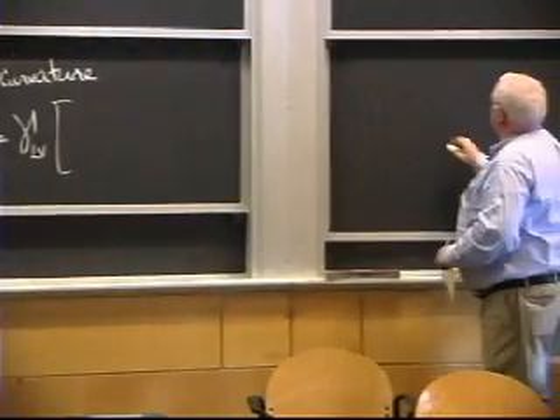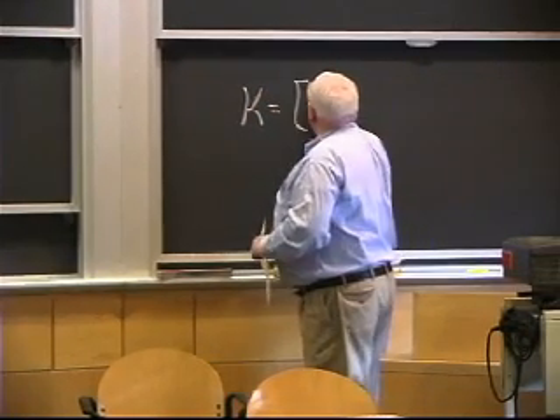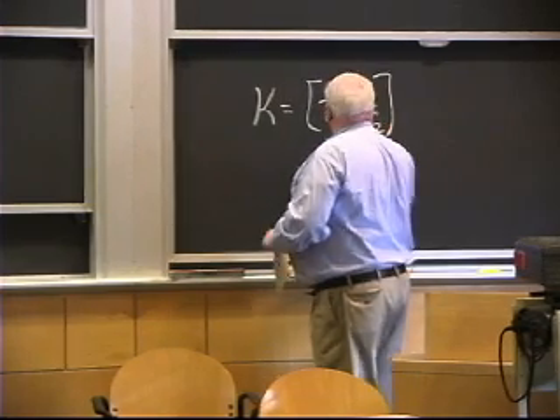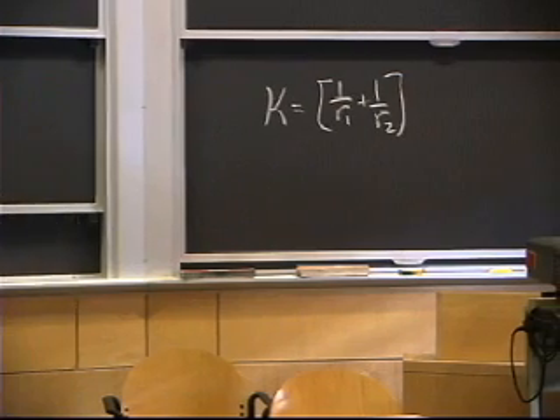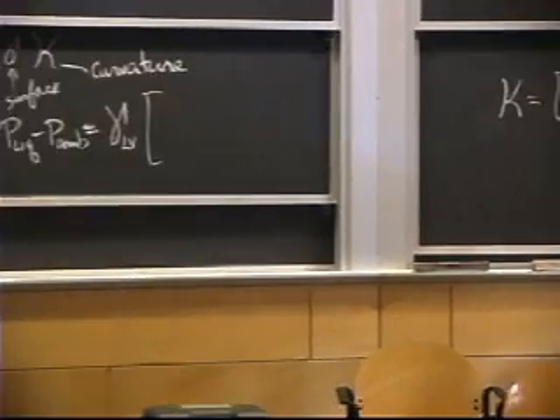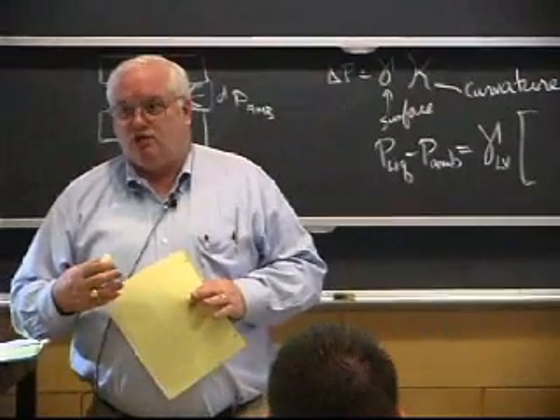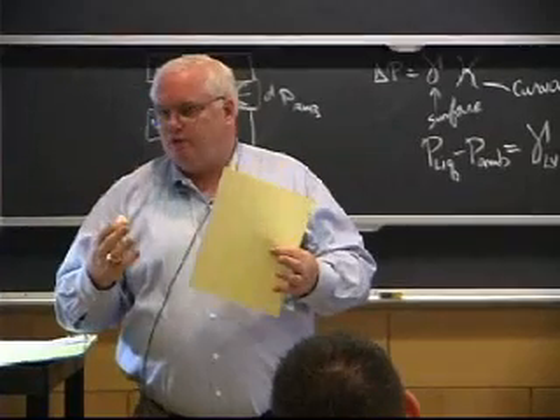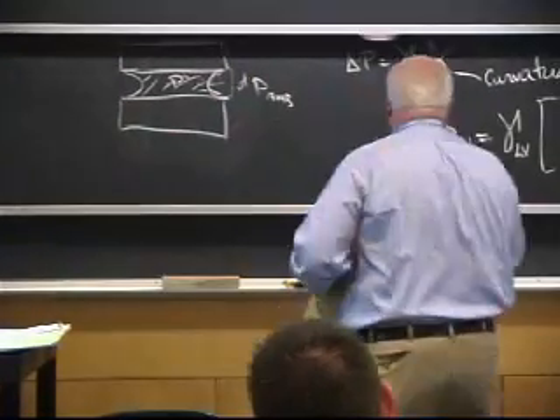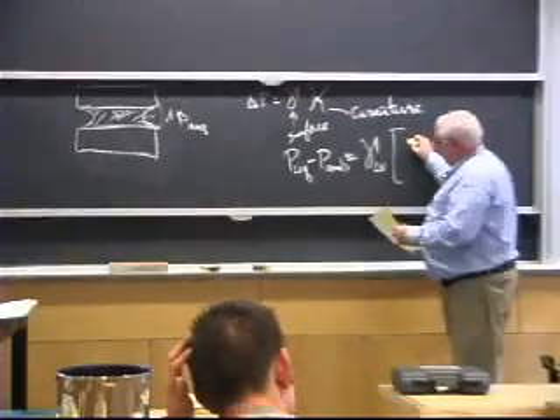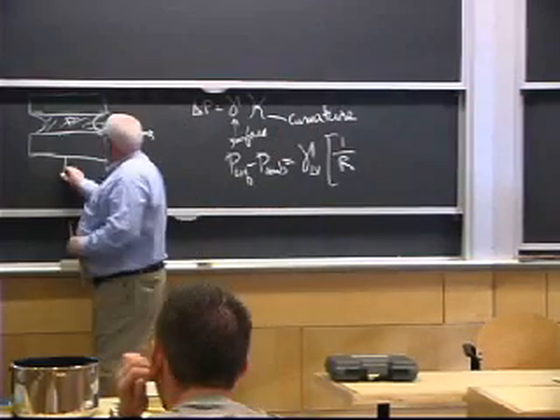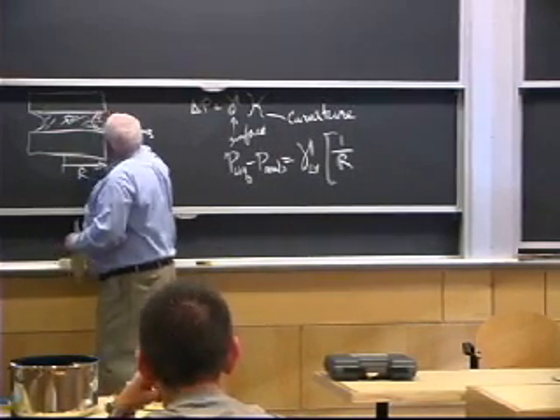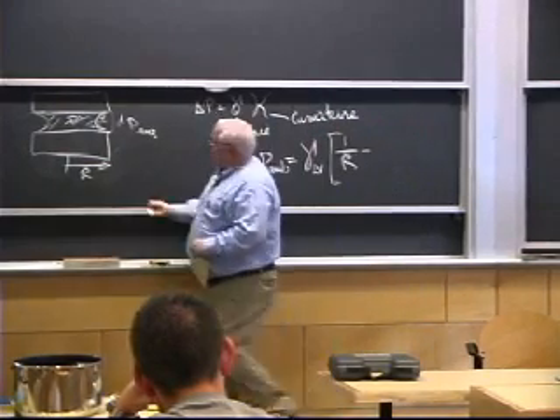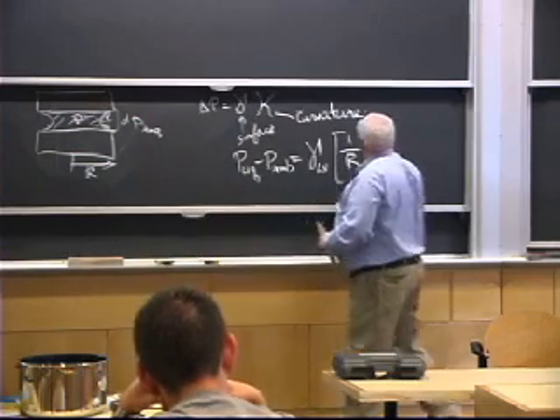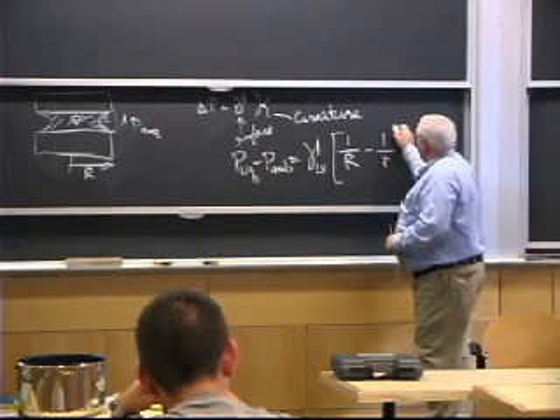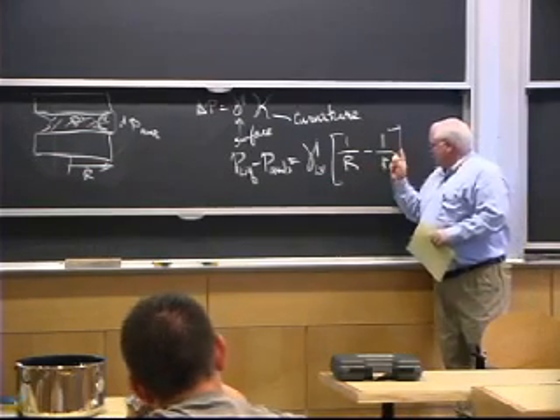The curvature in general of any surface is 1 over R1 plus 1 over R2, where R1 and R2 are the two principal radii of curvature of the surface. So for a sphere, R1 is equal to R2, and the curvature is 2 over R. And so it turns out the pressure differential inside a spherical balloon or a spherical bubble is 2 gamma over R, right? Because it's just gamma times the curvature. In this case, it's 1 over big R, capital R, which is this R, and then it's this little r. But that little r, the curvature here, we're defining the curvature from the center point of this thing. That little r is negative in terms of the center point. And so it's 1 over big R minus 1 over little r is the curvature of that surface.